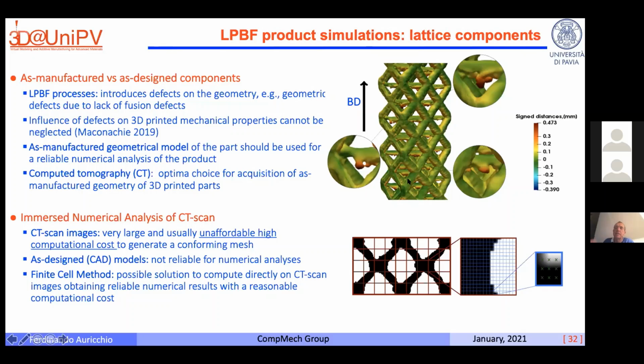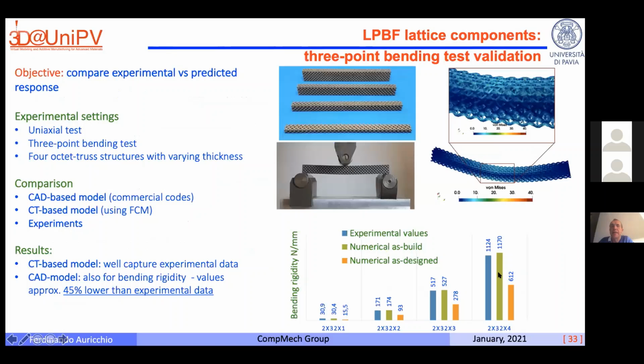So the idea here is, again, to go toward immersed technology. If you immerse your CT scan images inside a much larger domain, and you describe your geometry with refinement on Gauss points, and run the simulations, you can get a much better response. And you can see here the comparison.